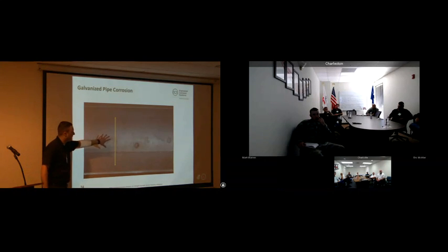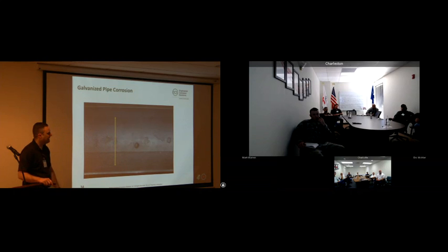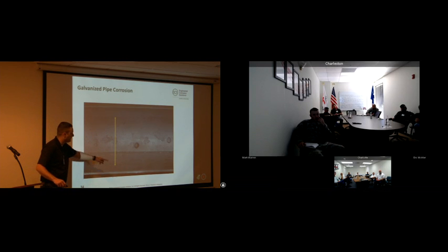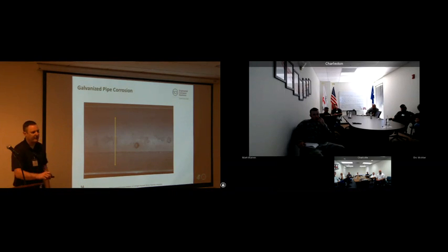The metal loss around there, there's virtually none, but we've got through the wall failure. I think that was about a 1/4 inch failure. The other thing to notice is this flow seam is completely intact. This piece of pipe was actually heat treated.